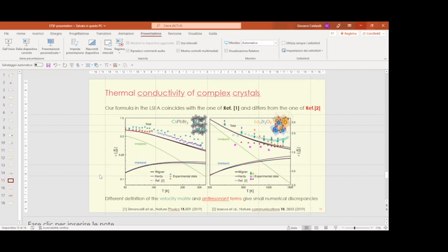Yes, they use exactly the same definition of the heat flux, but they actually introduced the phonon self-energy, so included anharmonicity, in a slightly different way. So we derive a quantum approach, we introduce anharmonicity via the spectral density, so via the phonon self-energy, in the frequency domain, as is the common way of doing it in a full quantum approach. Instead, they basically use an assumption on the real time. So they basically introduce anharmonicity as a scattering rate directly on the real-time expression of the Green's function.